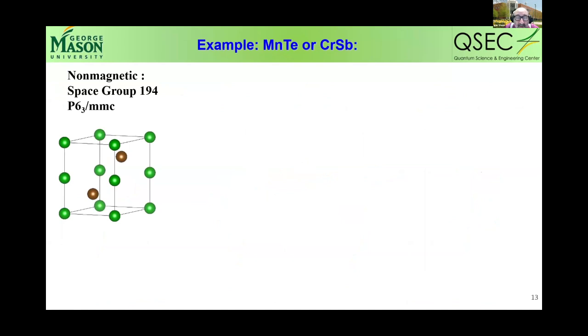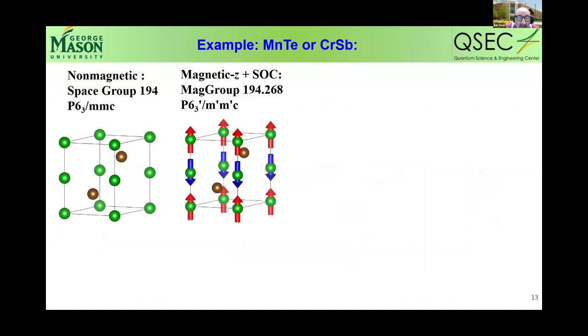So let me give you an example on these structures we already considered: manganese telluride and chromium antimony. These are the two most popular crystallographic motifs for altermagnetism. The other one is rutiles, which is unfortunate because manganese telluride is a self-doped semiconductor and chromium antimony is a metal, so many things can be studied there. So far, all known magnetic altermagnetic rutiles are strong Mott-Hubbard insulators, like manganese difluoride. There was one promising candidate, ruthenium dioxide, which turned out to be just an imposter. It's not magnetic. Later today, Roser Valenti will talk about that. But anyway, rutile is a very neat structure, but we want to find better examples. And this structure works better. In fact, there are direct measurements of band structure on both of them, which confirm the theory.